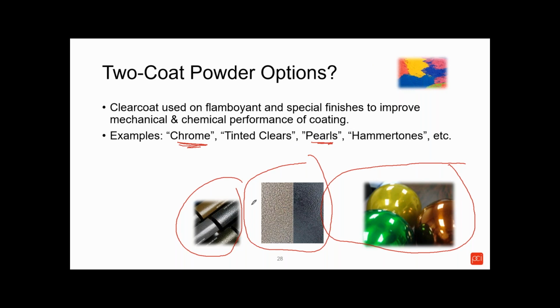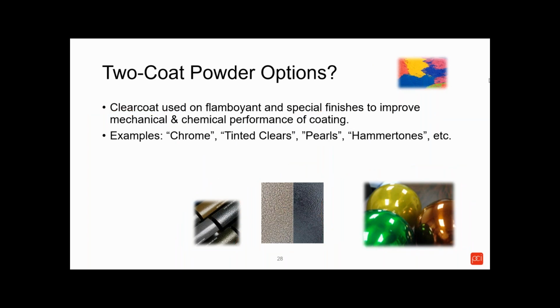These are products that have a very high appearance requirement, but they don't really bring along with them very good mechanical performance like scratch resistance or hardness. So the only way to make them work in this particular application is to put a clear coat on top. The clear coat is just to make these special finishes achieve the mechanical and chemical performance required for this application. And that's what made it a two-coat process.